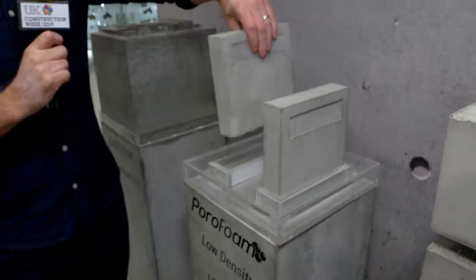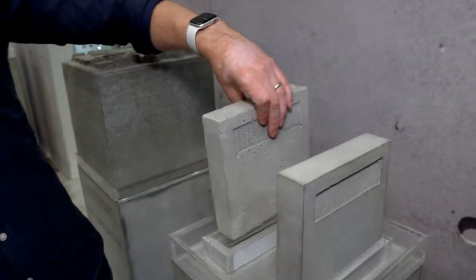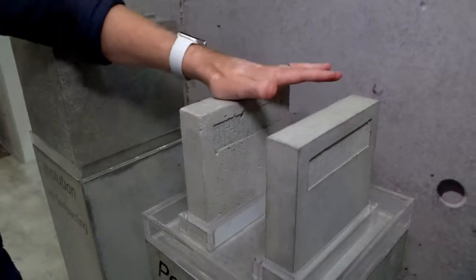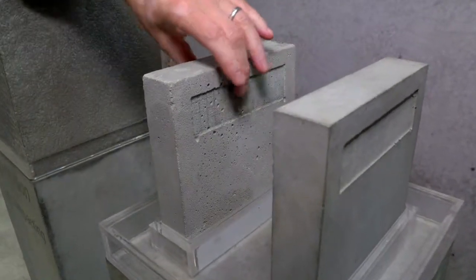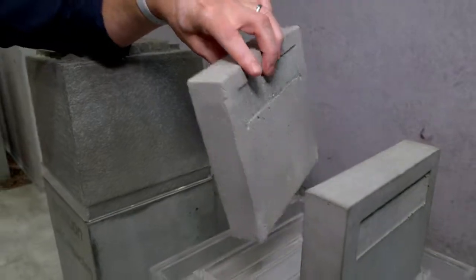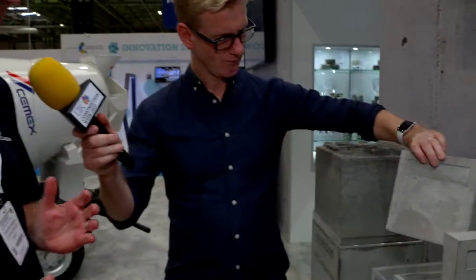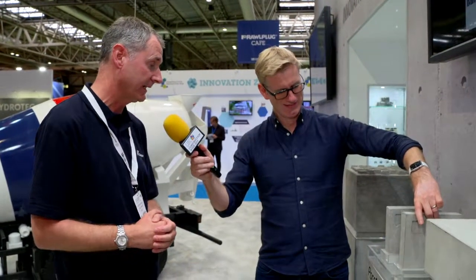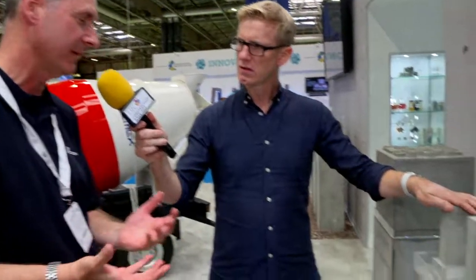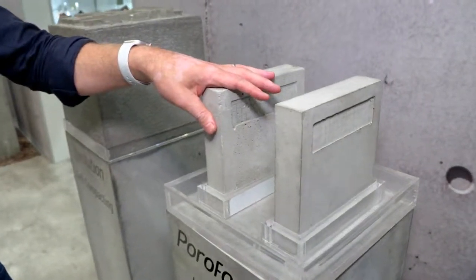Now, here, that is so very light. Porofoam. Our Porofoam low density concrete, with a very engineered and bespoke set of admixtures, enables us to design concretes down to oven dry densities of 300 kgs per cubic metre, when typically a normal weight concrete would be around 2,300 or 2,400 kgs per cubic metre. A change of density enables you to design concretes with a range of compressive strengths as well. So at 300 kgs you'd be down to maybe half a megapascal or 1 MPa at 28 days.